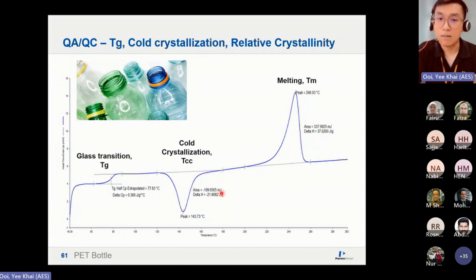But this is a metastable state, meaning at a higher temperature, it is going to melt. Hence, for semi-crystalline material, if you heat up slowly, you are going to get TG, recrystallization of the molecules, because now you are allowing it time to recrystallize or repack itself into a crystalline form, and then melting at a higher temperature. So this is the typical curve you're going to see.